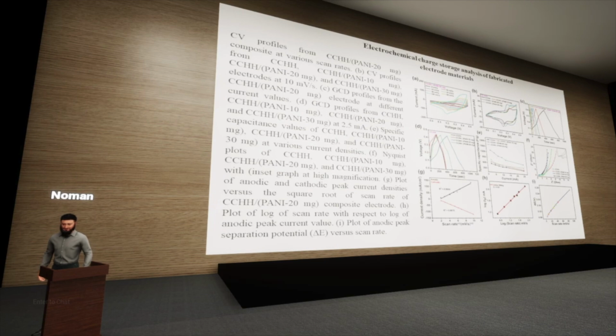After performing the structural characterization, we checked our material for the electrochemical energy storage device. As discussed previously, for the electrochemical testing we used the three electrode assembly. This is the cyclic voltammetry curve of the best performing material, which was the 20 milligram addition of polyaniline in cobalt carbonate hydroxide hydrate. This is the comparison of all the samples. We can see that the 20 milligram addition of polyaniline shows the maximum area under the curve, and it means that it can accommodate the maximum charge.